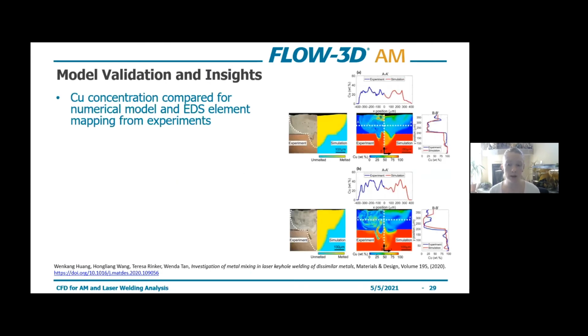So looking into their validations, what they compared was the EDS element mapping from experiments with simulation results from Flow3D AM. So if you look at these images, experiments on the left, simulations on the right, and what they're plotting here is the copper weight percent. So visually, we can see very good agreement between the 2. And they also looked at the concentration of copper at any given point along the X and Y axis, comparing simulations and experiment, which in both cases we have good agreement as well.